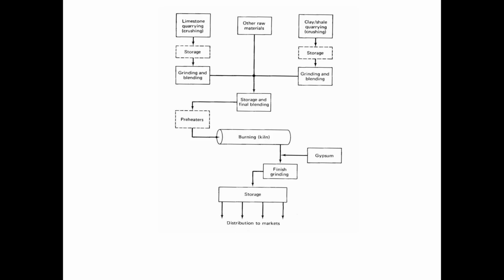What we get out of the kiln is an ugly looking mass of a material that's referred to as clinker. So that's not our cement. We're not quite to the point of cement yet, but we get these gobs of material that are referred to as clinker. And so then we have to take that clinker and we have to grind it down into the material that we refer to as cement. As part of that process of taking the clinker and grinding it down, we may introduce some gypsum into the mixture at that point. Gypsum helps to control the set time of our cement, so the amount of gypsum that is added will depend on the proportion of the other materials that are going into our cement.